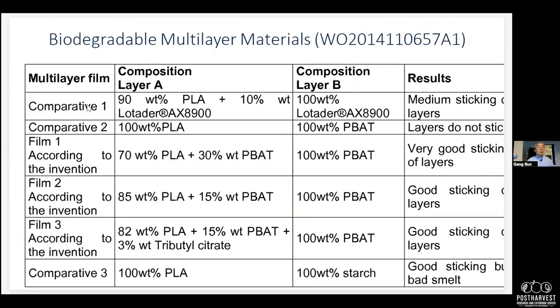Also, I tried to find more multi-layers from the bio-based materials. And this comes from a patent, because nowadays there is more proprietary information for these multi-layers. So this comes from the PLA. You have a layer A, and then also a layer 2 with a different material. The common thing here is you see PLA, PBAT. Remember I said PBAT is a biodegradable polymer, but it comes from a petroleum base. That can be produced at lower cost. Obviously, it brings in other functions that the pure PLA may not have. So overall, you will see such.